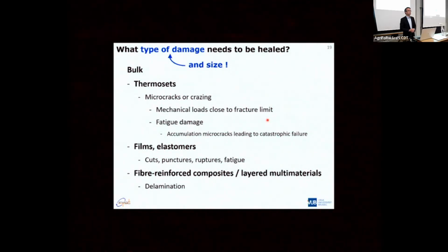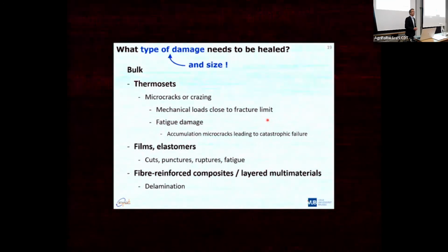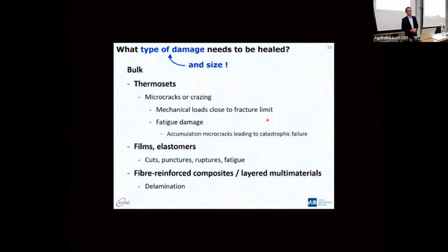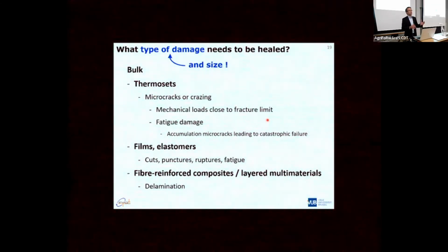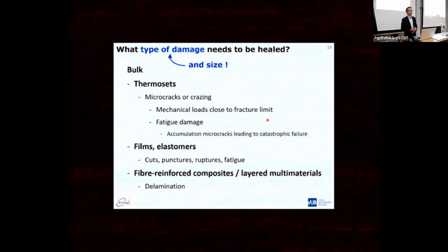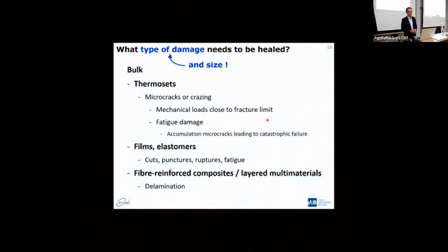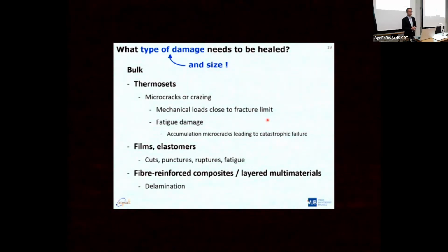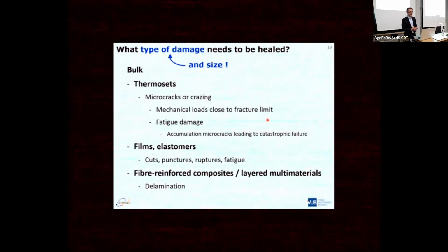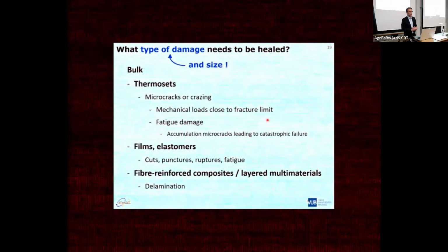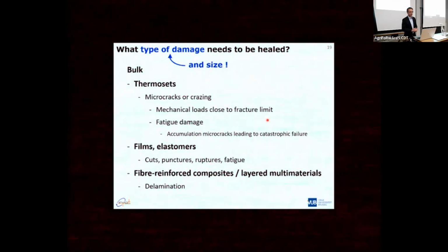Same goes for fatigue damage. Yeah? The average sample might live for 1 million cycles, but some of them will fail after 100,000. So it's not easy to induce, although you can apply in a controlled way the loading and the number of cycles and so on, it will not give you the same amount of damage each time. For films and elastomers, things like cuts and punctures, ruptures as a result of overpressuring are of course important, but also fatigue damage is definitely one of the types of damage that is quite important. When you go to fiber reinforced composites, layered multi-material systems with different materials, different polymers, or really different kinds of materials inside, of course, again, delamination is very important, and again, quite difficult to introduce in a very controlled way.